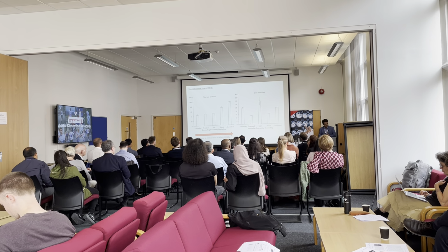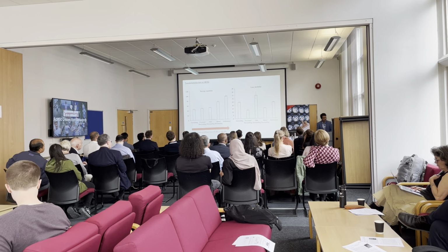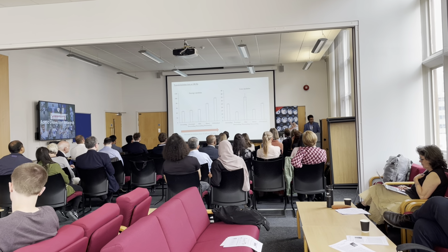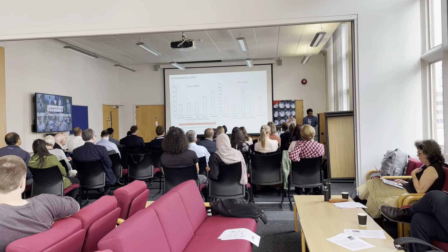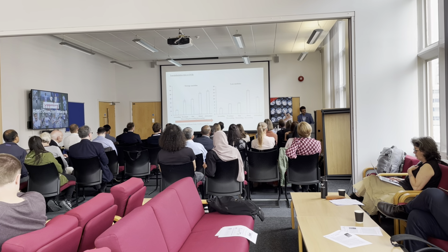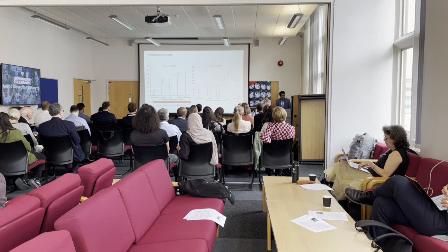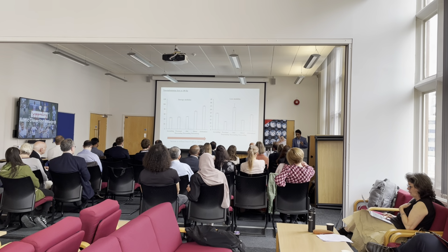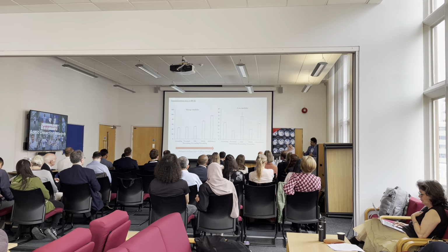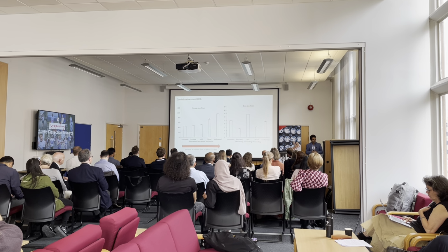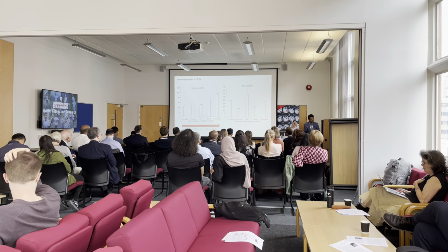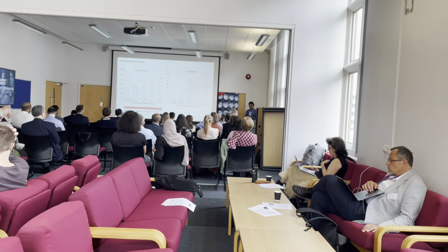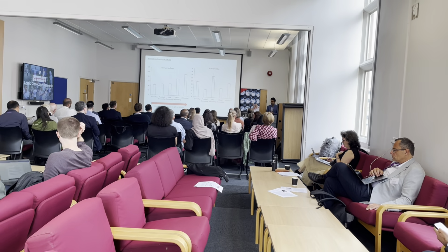And then when the indentation frequency was increased up to 100 Hz, we were also able to obtain an increase in the storage modulus across these regions as well. As you can see here, at the ascending region the storage modulus was approximately 10 kilopascals, but as we increase the frequency, the storage modulus also increases across all these regions. So it goes from approximately 40-45 kilopascals to around 100 kilopascals. Again, the same effect was not observed in the case of loss modulus, and I'm still trying to understand why.